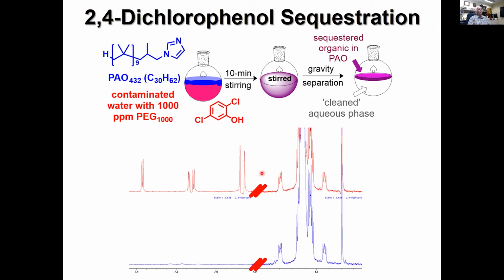So you can determine that this started off at a particular concentration, let's say 40 or 50 ppm. Then when you heat it, stir it, and let it do a gravity filtration, you can look at the clean aqueous phase. And the clean aqueous phase—all you see is this C13 satellite of the PEG. This peak is essentially gone. This peak is gone. This peak is gone.